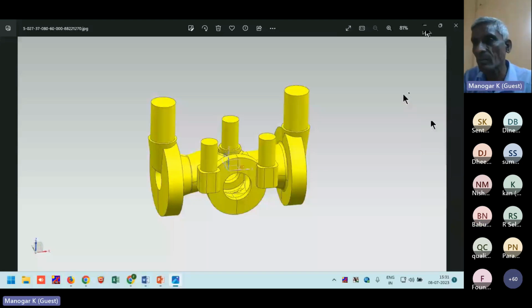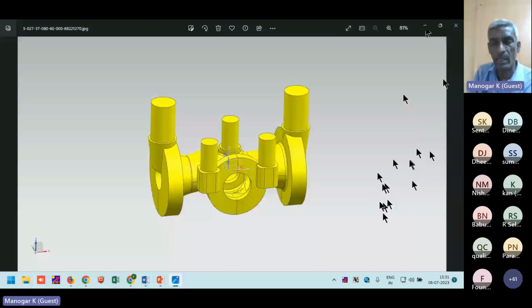Okay. That is like a step in-gate. The bottom in-gate is always advisable, but making a bottom gating, especially in SG iron, is difficult unless you use a refractory gating. Parting line gating is what we are always using. In that I explained whether you can use an in-gate in the top or in the bottom of the runner. So using the parting line runner, in-gate and runner over the in-gate is a preferable position as per my experience. And a top in-gate connecting to the riser is best to feed the riser with hot metal. If it is possible for you to keep such a gating system, it is good. That depends upon the casting nature or your process. If you are using a vertical parting and cake mold, then all this is possible.